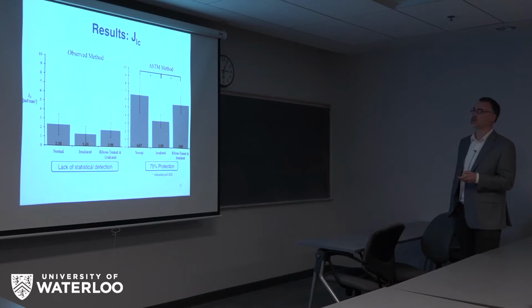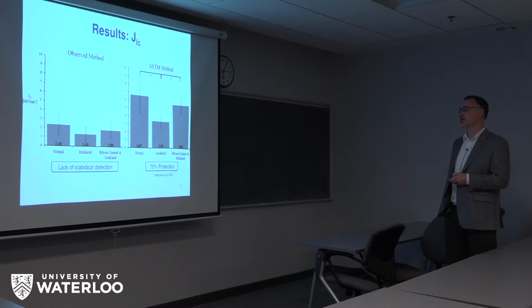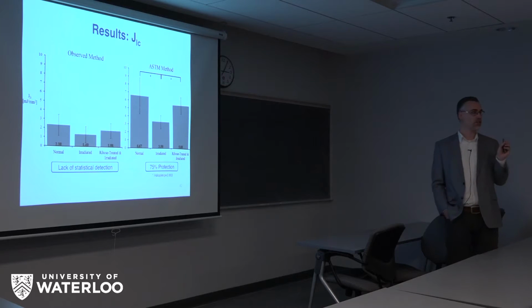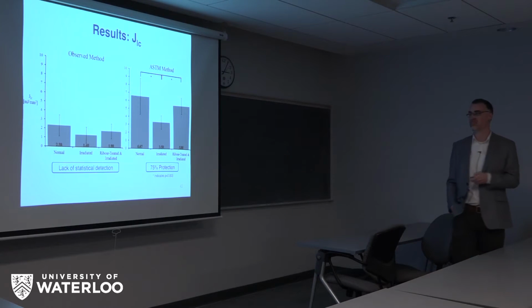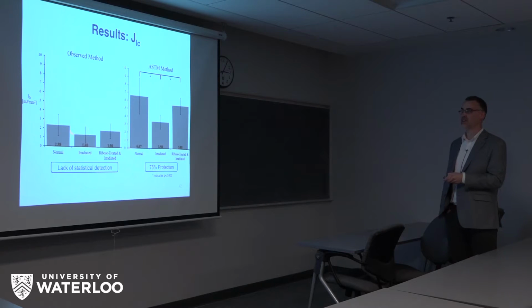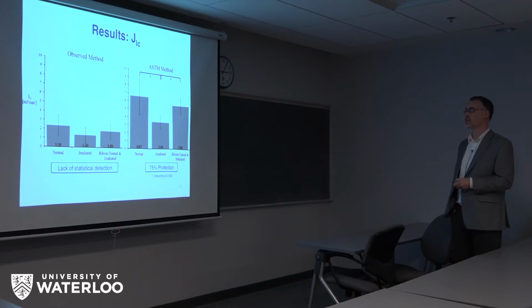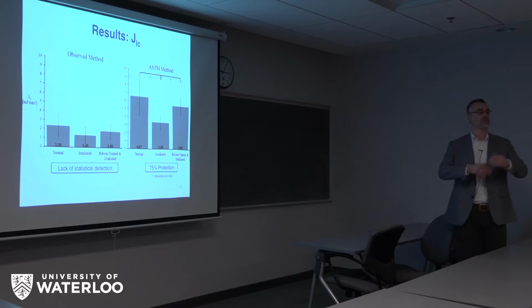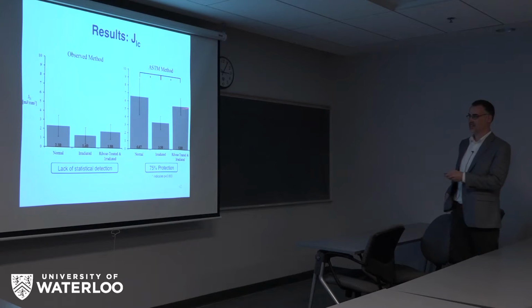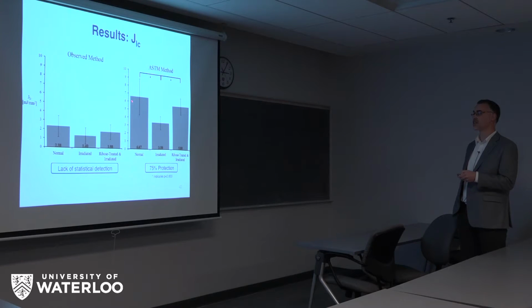As I mentioned, I'm going to talk mainly about J1C. Turns out that at very small crack growth, using our optical method, we really couldn't statistically draw out differences in the means. But when we use the ASTM method, which allows for a little bit more crack growth, we get this separation. And in fact, we get 75% protection. It's about 50% loss here from normal to irradiated, and then 75% protection. And statistically, these two we couldn't separate, but we have the statistical difference here and here with very small p-values.